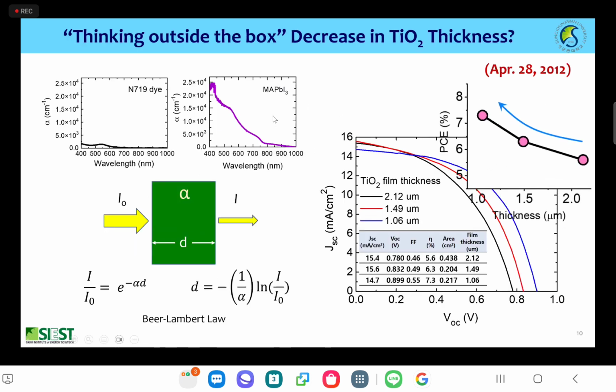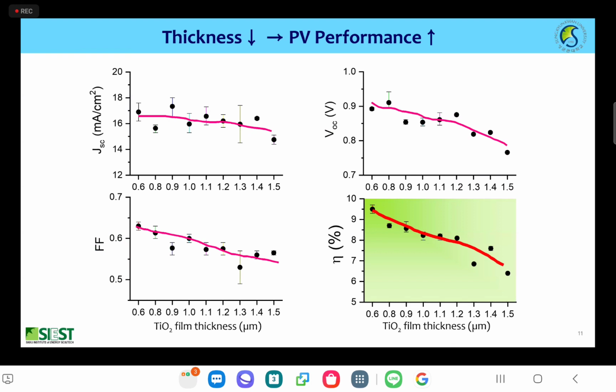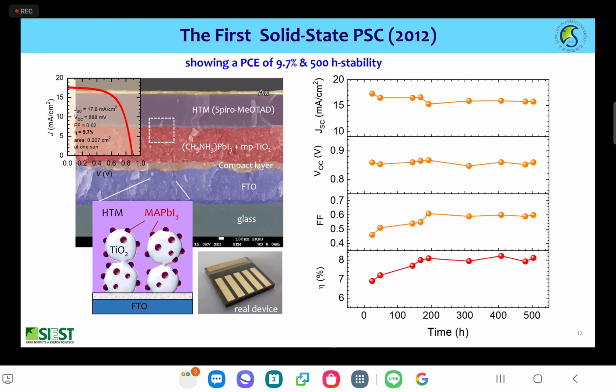Therefore, we revisited the absorption coefficient of the perovskite, which is 1 or 2 orders of magnitude higher than that of the conventional ruthenium complex organic dye. Based on the Beer-Lambert law, you don't have to increase the film thickness because of the high absorption coefficient. Then we decreased the film thickness to 1 micrometer, and achieved higher efficiency because of the higher open circuit voltage. Further, we decreased the titanium oxide film thickness to 0.6 micrometer, and a gradual increase in power conversion efficiency was observed because of the increased open circuit voltage and fill factor without sacrificing short circuit photocurrent density. This is the first solid-state perovskite solar cell that we completed in 2012.